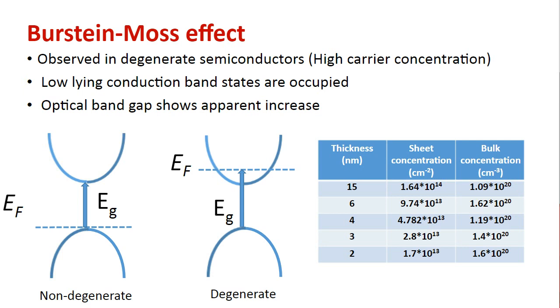we see that the band gap has apparently increased, and it has increased by the amount the conduction band is occupied. I'm showing you the thickness and the concentration numbers that we extracted from our transport measurements, and these are really degenerate semiconductors as we are hypothesizing, and this is something that even other groups have pointed out. So we see an apparent increase in the band gap due to the Burstein-Moss effect because the conduction band is partially occupied. So it is a kind of quasi-metal, more like a metal than a semiconductor in the strict sense. Plus, we observe this finite size effect that we are really hoping to uncover here.